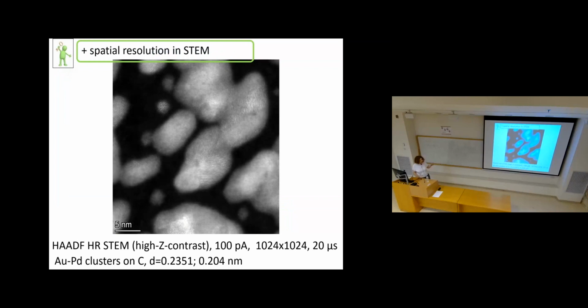Okay, and this is the high resolution STEM image on the standard gold grating replica. So the replica is a gold palladium clusters on carbon. So what you see, the lines you see are the periodicity, the high resolution, atomic resolution image of gold palladium cluster, and the distances you see here are mostly 2.3 and 2.0 angstrom of the gold lattice. So this is something routine, more or less routine with this microscope. This was totally impossible with F20.